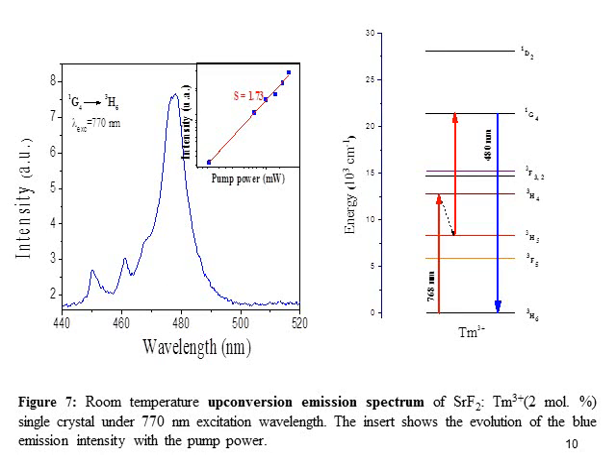The blue emission at 480 nanometer is only obtained by upconversion under infrared excitation around 770 nanometer. This phenomenon is interpreted by the successive absorption of two photons which populate the 1G4 level, de-energizing directly in the fundamental level.